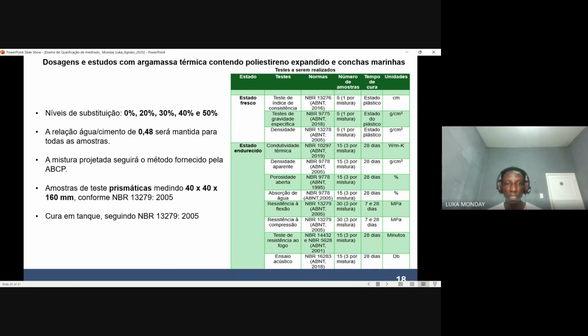The following substitution level is going to be used with respect to the methodological approach. A 0 to 50% substitution level is going to be used for both materials. A water-cement ratio of 0.48 is going to be maintained throughout the mix, using a prismatic sample mold of 40 by 40 by 160 according to the Brazilian standard. And the curing is going to be done as specified by the Brazilian standard.